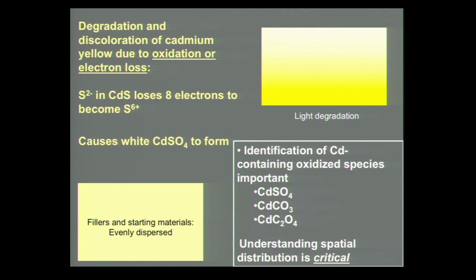So in the case of cadmium yellow, we see it changing chemically as a result of oxidation, or losing electrons. And specifically, it's the sulfur that starts off at 2- and loses 8 electrons to become sulfur 6+. And when that happens, the cadmium sulfide is converted to white cadmium sulfate. And so you can get this type of layered structure. And so it's critical not only to identify the presence of cadmium sulfate, carbonate, and oxalate in these paints that are changing color, but we also need to know the spatial distribution of these compounds as well.